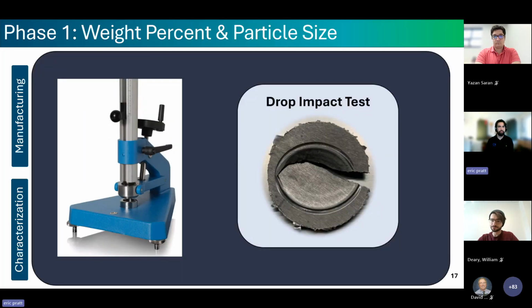Impact testing is a much more critical factor for our use case. It's a pretty simple drop weight test. A specific mass is released from increasing heights onto our injection molded specimens until it fails. We followed a modified ASTM D4226 protocol, and we treated this as our most critical test that we ran because impact is the failure mode these spools are actually going to encounter in the field.